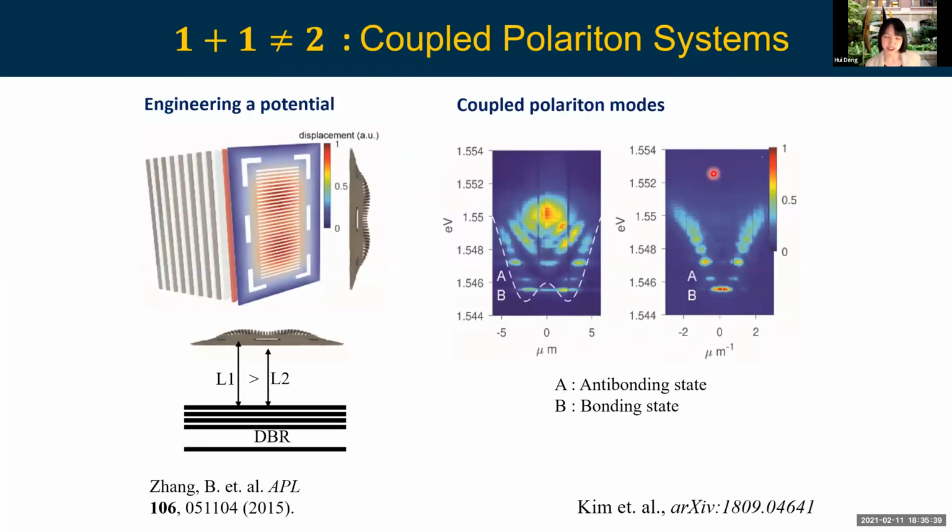Right? And we can probe that physics quite easily with such a photonic crystal grating type of mirror. And we hang those mirrors above an air gap with those tethering structures around it. And there will be strain when we remove the underlying layer. So this grating will be buckled, and that will translate to different cavity length, and that will translate to different cavity energy, and that will translate to different polariton energy. And that gives us an effective potential for the polariton mode.